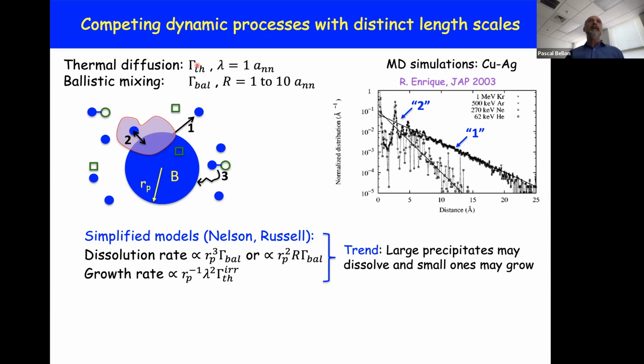So here, the thermally activated jump frequency. The jump distance for this diffusion is 1 nearest neighbor distance. In contrast, there is this forced mixing, which we tend to call ballistic mixing, following the nomenclature introduced by Georges Martin. This ballistic mixing takes place at a different jump frequency, which is related to the displacement rate or the damage rate. And the range of these relocation events or replacement events is now larger. It ranges from 1 to 10 nearest neighbor distances.